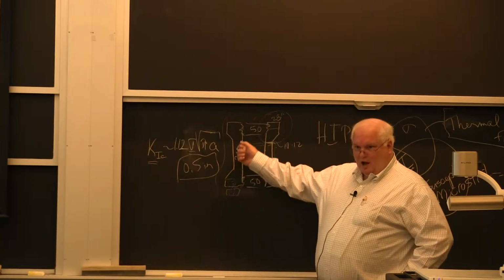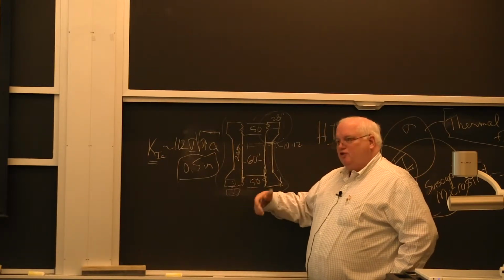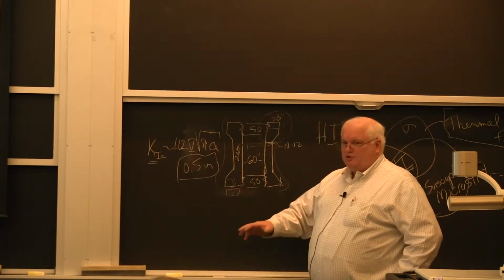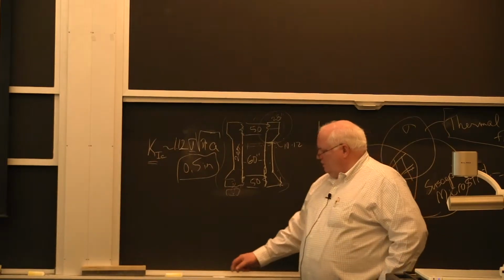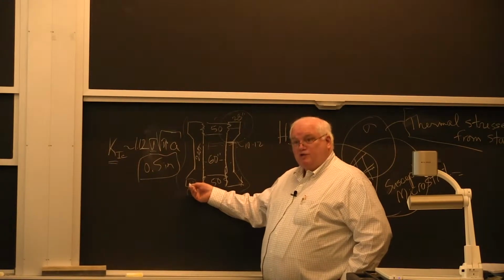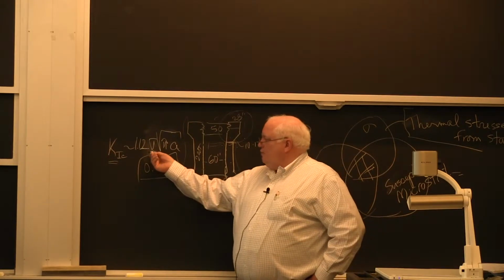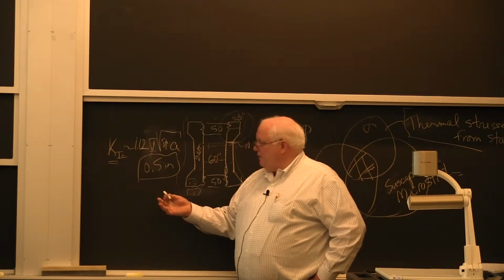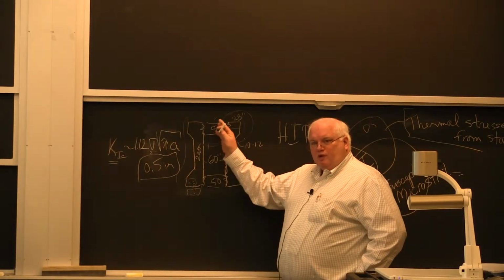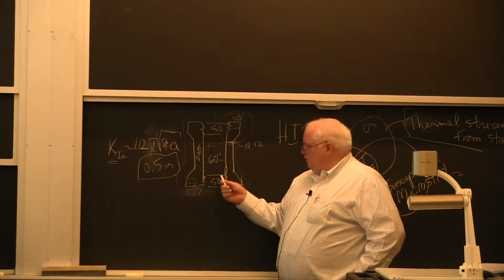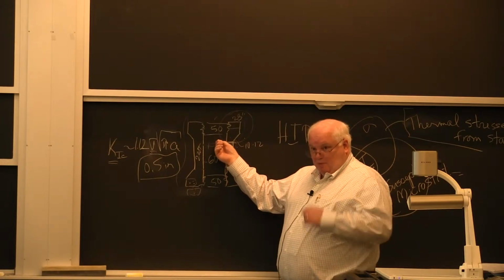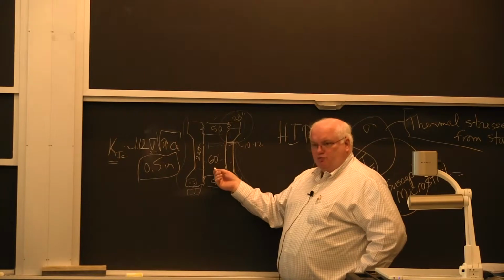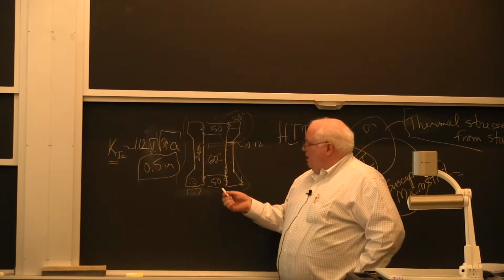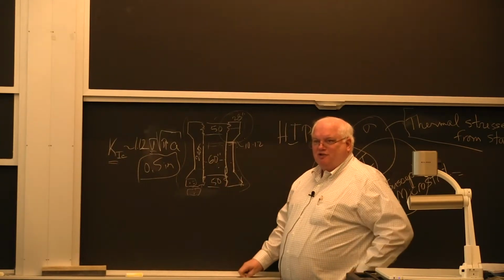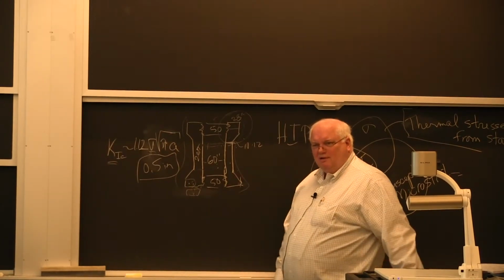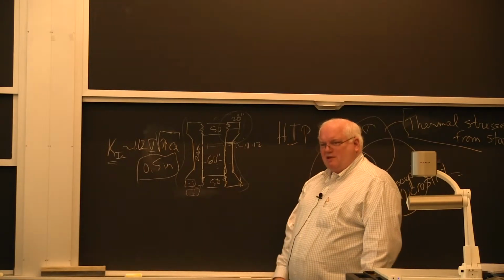Because this was heat treated to a high strength, so it's quenched and tempered. And during the quenching and tempering operation, steel composition, furnace wasn't right, whatever, okay? So you have three people on the hook. Japan Steelworks didn't supply what was specified. The people who operated didn't worry about the thermal stresses, okay? They could have slowed the whole process down by bringing things up to temperature before they pressurized it. You can't do it exactly because you don't actually have pumps that pump in 20,000 PSI argon. At room temperature, you put high pressure argon in here, which might be 1,000 or 2,000 PSI. And then when you heat it up, thermal expansion gives you the rest of the pressure. It's a closed vessel. I mean, you're building a bomb here, okay? There's no pressure relief valve on this at 20,000 PSI, okay?